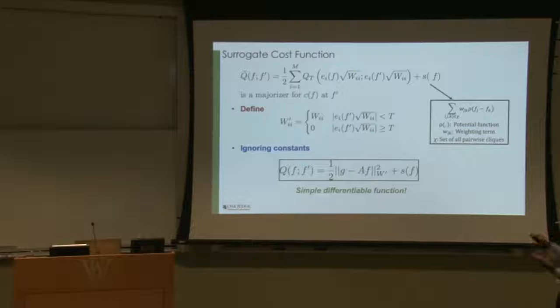And it turns out one of the cool things is that we've essentially turned a complicated non-convex function into a sequence of simpler convex functions. And it has a nice interpretation. It essentially says, okay, I have this data which has some effects that I don't model very well. So what I'll do is at every iteration, I start with a guess for the 3D volume. I project it. I find the difference between the measurement and my prediction. And those areas where the error is large, where I'm not able to fit it very well, in the next iteration, I just kind of drop those measurements out.